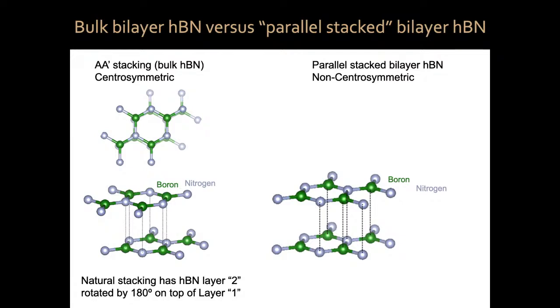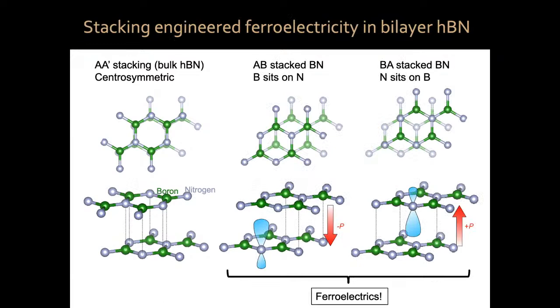Now, that's very uncomfortable. The boron atom doesn't like to be on top of a boron atom, and the nitrogen on top of a nitrogen atom. So what happens is that the system shifts laterally, and it goes into one of two options, an AB stacking configuration or a BA stacking configuration. And it turns out that these two different configurations have opposite electric dipole moments. So if you can switch somehow magically between these two, you have a switchable ferroelectric. You can perhaps make a memory element, for example.